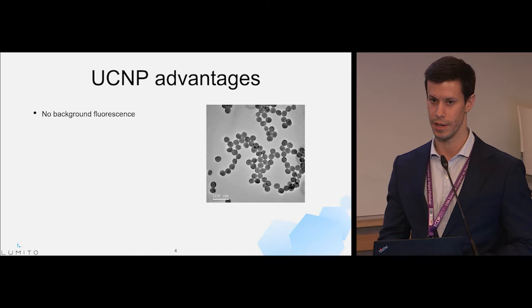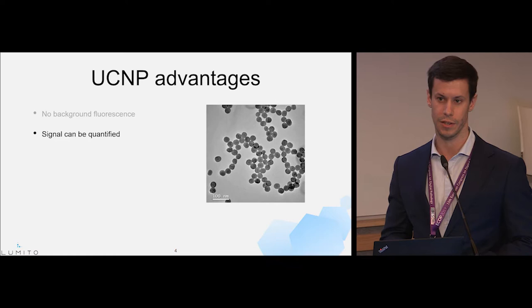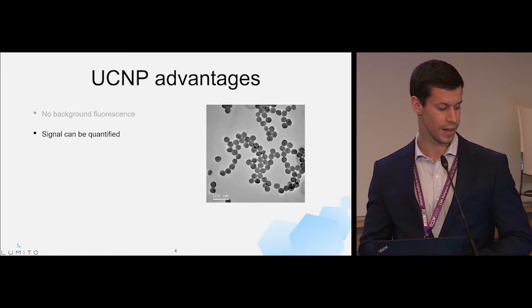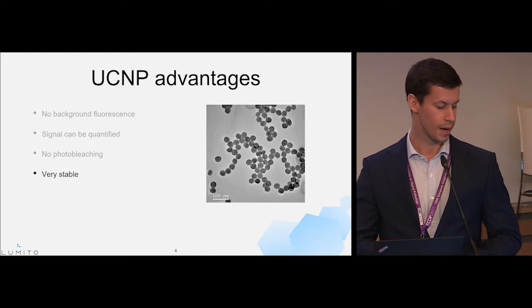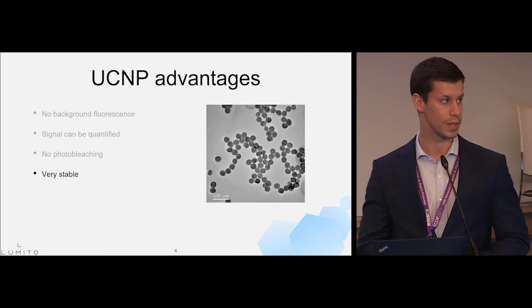The signal can be quantified because there is a direct correlation between the number of particles and the signal strength. There is no photobleaching — you can image slides stained with UCNPs many times and over a prolonged time. They are very stable, and slides stained with UCNPs can be stored at room temperature without any problems.